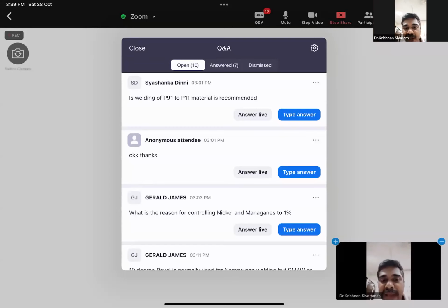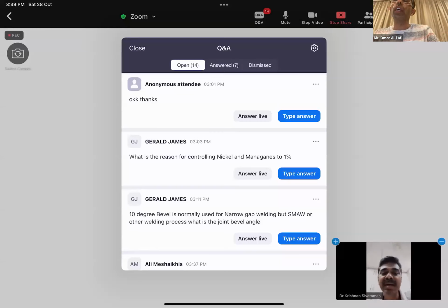Omar, there will be a challenge here if you try to join P91 to P11 directly. The PWHT temperature for P91 is going to be quite high. Yes, so getting P11 material to that PWHT temperature is a big challenge. Another way to handle this is by providing another spool of, say, P22 in between. Yes, or a transition piece. This is one of the points to avoid such a configuration, to have a transition piece of P22 material between the P91 and P11.